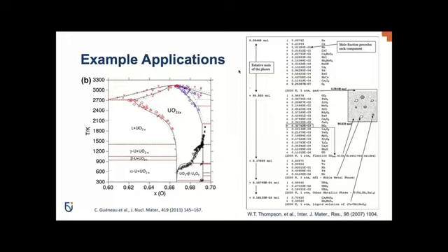And for this particular fuel, which is typical burnup for CANDU fuel, fairly low for LWR fuel. But what you can do here is you can see, and I'll just use my pen here, this is written in the FactSage output. You have these different blocks here corresponding to different phases. The first one I've outlined here is the gas phase, where we see that the number of moles of the phase is written here in this format, followed by the mole fractions of different species within the gas.